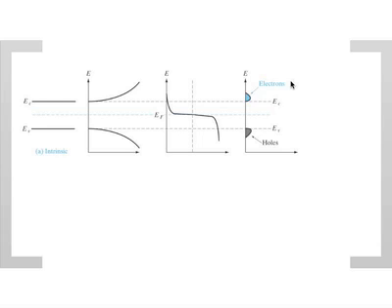In an intrinsic semiconductor, most of the electrons will be concentrated at the bottom of the conduction band, which is exactly what the equations tell us. And most of the holes will be concentrated at the top of the valence band. Qualitatively, you can see this. Let's look at the electrons for a second. Although the available states increase here, so one would expect many more states available, why wouldn't electrons be there? But you can see the probability is very small. It falls exponentially, and the product, of course, gives you some optimum value near the conduction band.